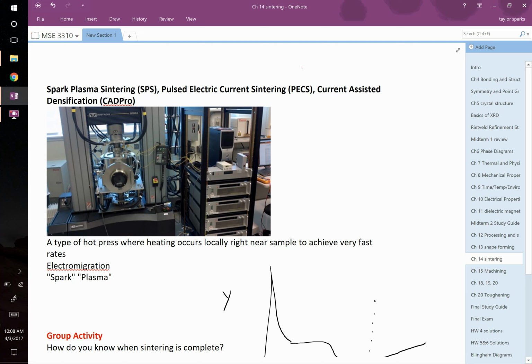Probably you could go faster, but if you just expose it to air, that'd cool too fast. It's a graphite die inside of here, and your sample might be heated up to 1300 C, where it's radiating quite a bit out. If you were to expose oxygen in there, that radiative heat has the inside edge of the steel quite hot. It would start to corrode, and other things might start to corrode. Your electronics, your thermocouples might be air sensitive. So generally speaking, you don't open this until you're around 200 degrees Celsius.